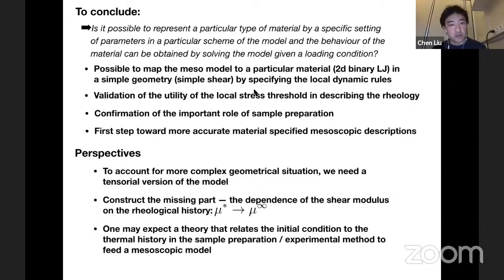And we also confirmed the important role of the sample preparation in the transient dynamics. What we suggest is that the initial stress field and the initial field of thresholds actually encode relevant information of sample preparation to the rheology afterwards. And we think that we made a first step to develop more accurate material-specific mesoscopic descriptions. And then at the end, some perspectives.